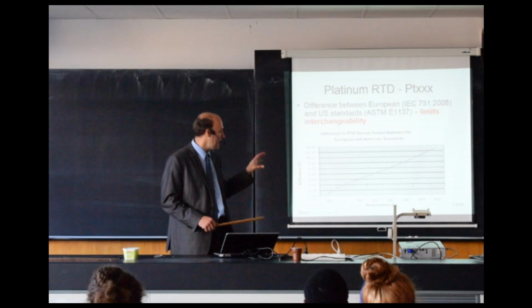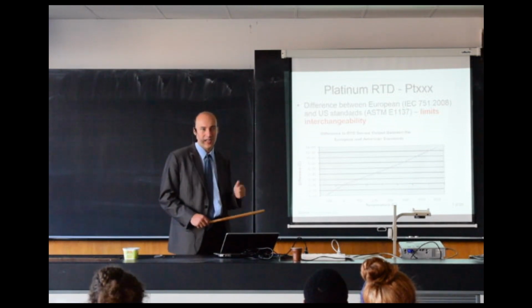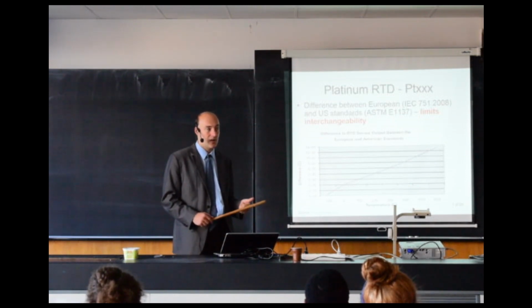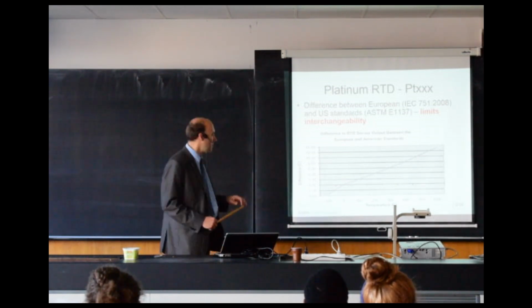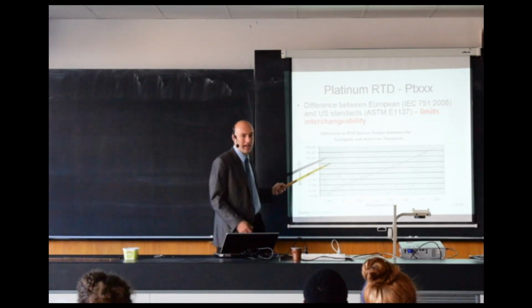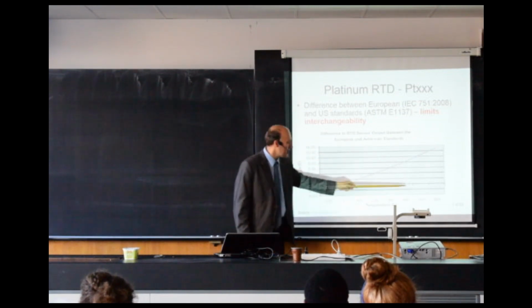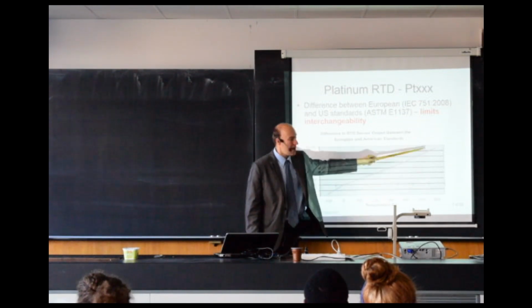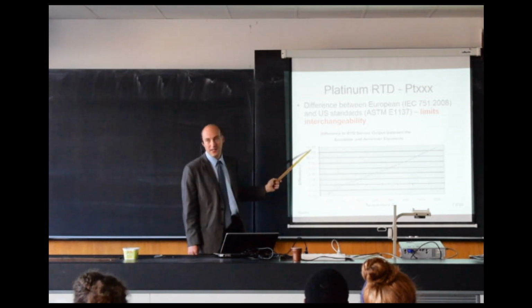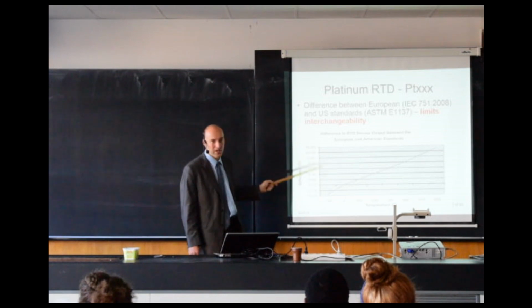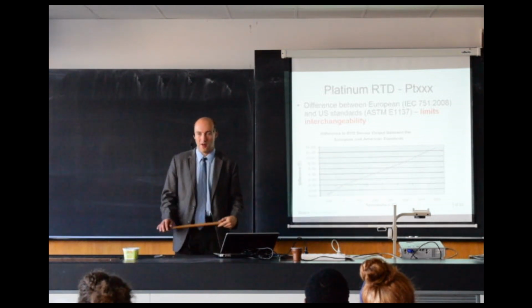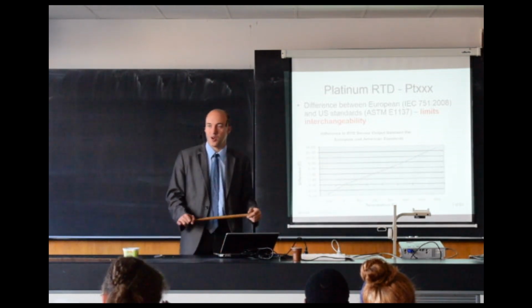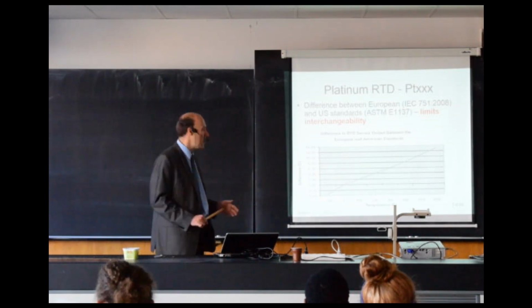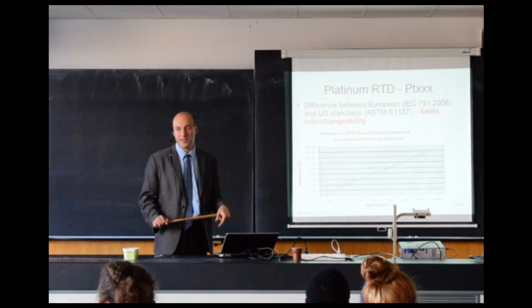So in the previous table, we've seen that at 600 in a Class A sensor, I can measure within 1.3 centigrades. But just by using the standard that's not adapted to my application, I can add an additional error of up to 13 centigrades, which is roughly 10 times larger. So be very careful about this. Use preferably one standard that fits into your application, and if you need to reorder that, specify the same standard.